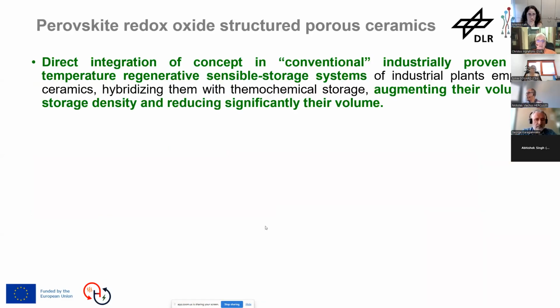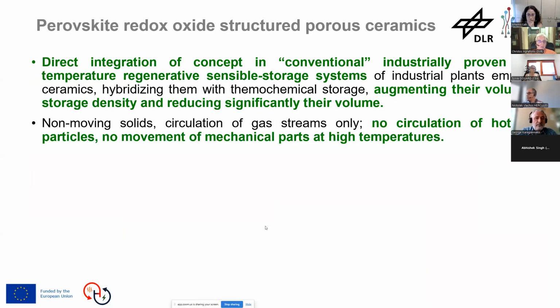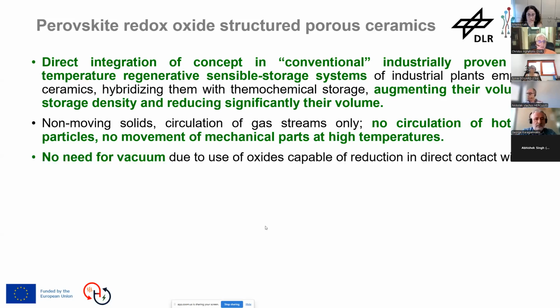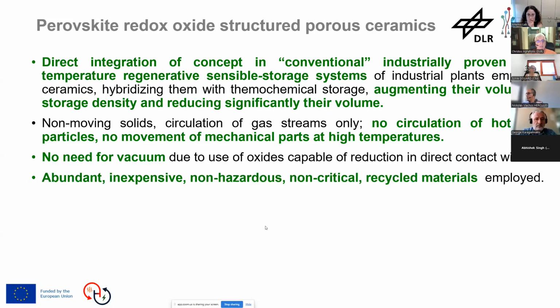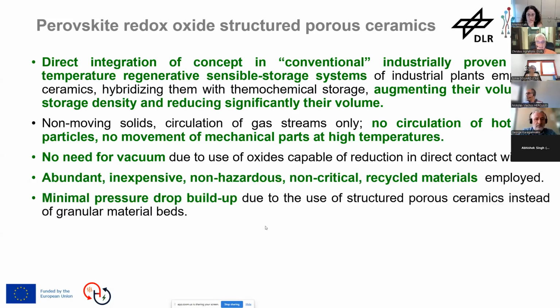So the last slide to conclude is that the idea is to integrate thermochemical storage within sensible heat in the same way that is performed currently with porous flow-through ceramics to produce more energy and store more energy per unit volume. Of course, the advantages of non-moving solids: only gases circulate, nothing solid moves, and there are no mechanical parts at high temperatures. Also, these materials can be operated under air both during reduction and oxidation, so we don't need vacuum. As we said, they are abundant, inexpensive, and non-hazardous, and can use reliable recycled materials as well. There is a minimal pressure drop build up due to the use of extremely porous ceramic structures.